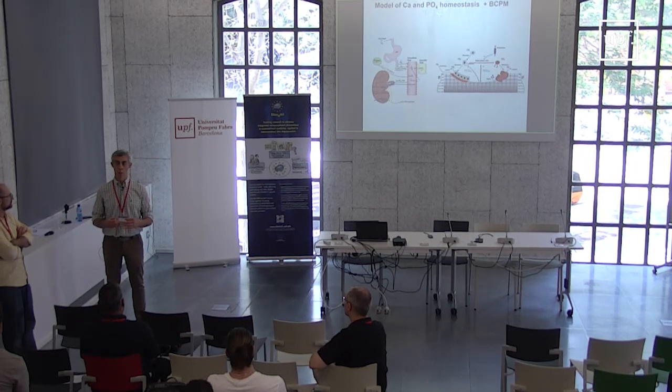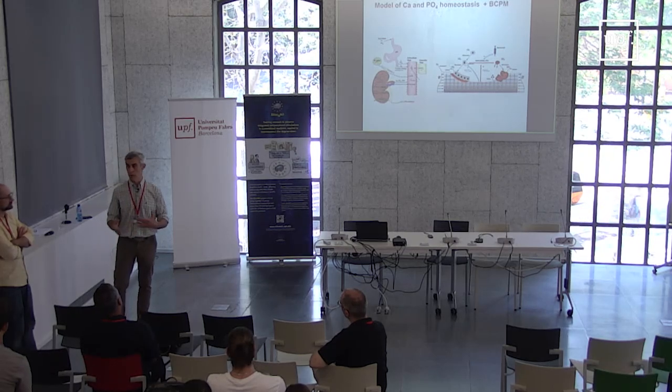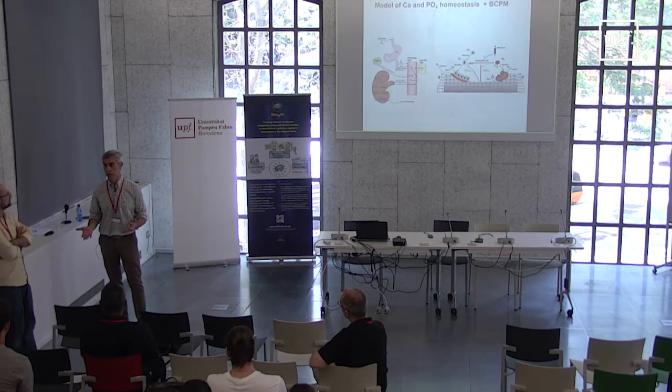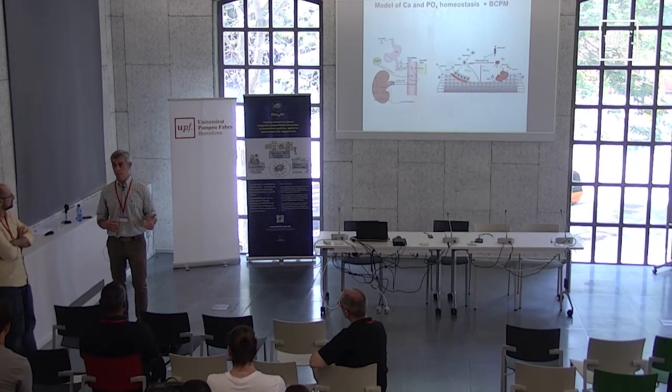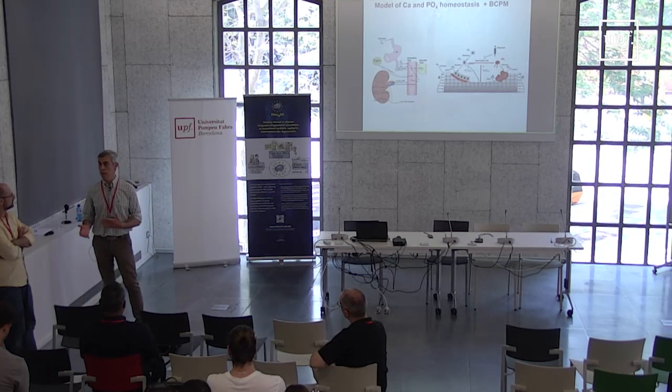So what we do know is that an excess of mineral content fragilizes bone. And in the case of antiresorptive drugs, this is a very important problem, because you're basically increasing your mineral content, and it reduces the viscoelastic properties of bone, which are useful to bear the loads in a more efficient way, certain dynamic loads.